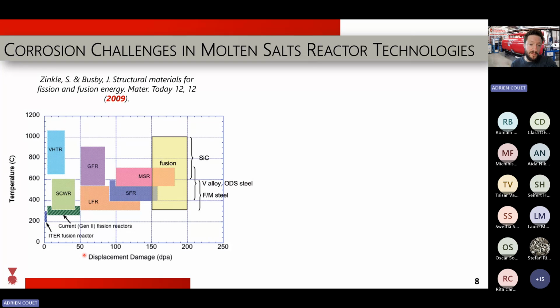because most of those defects that you create, most of these atoms that have been displaced, are going back to their original site or to a similar site very quickly, so the defects don't have a very long exposure, a very long lifetime, right? Thanks to this recombination of defects, you don't form a lot of defects, and you don't vaporize your material with just 1 DPA.